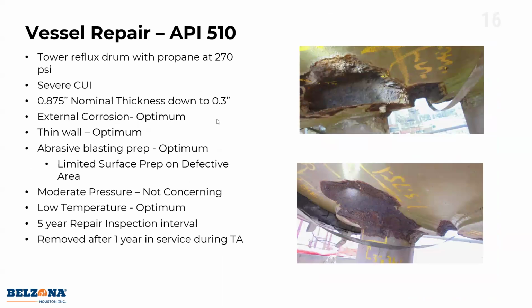But the example I want to go into in more depth is this tower reflux drum that had propane at 270 psi and severe corrosion, a 0.875-inch nominal thickness down to 0.3. Even though it's severe corrosion, it is external corrosion, so that's optimum. Thin wall, that's optimum. Abrasive blasting, that's great, that's optimum.